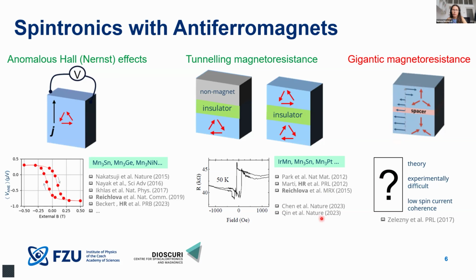And you see that one thing which makes them common is that in antiferromagnetic spintronics, these are not the simplest collinear systems, but systems having a somewhat more complicated structure, either triangular or non-collinear, non-coplanar. So these became, to some extent, the workhorses of antiferromagnetic spintronics. Manganese-3 tin is a fascinating material, manganese-3 platinum. All these effects were, in fact, observed or studied in these non-collinear systems. And before I go to these collinear systems, where you probably already know where I'm heading, let me just make a small excursion to spintronics with collinear antiferromagnets.